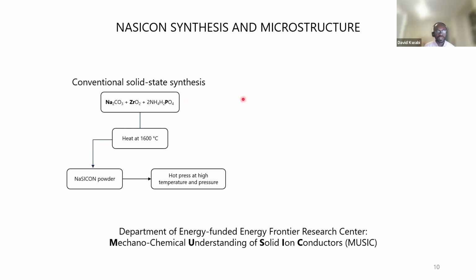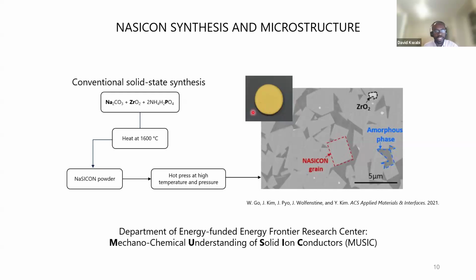One of the things we discovered fairly early on in our work is that the conventional way of synthesizing these NaSICON membranes gives rise to a very heterogeneous microstructure. The traditional way one synthesizes NaSICON is you take powders of sodium carbonate, zirconium oxide, and phosphate, mix them together, and heat them at about 1600 degrees C. That results in a NaSICON powder, which you can then hot press at high temperature to end up with a pellet of your NaSICON material, which you can then put into a flow battery. It turns out these materials are indeed excellent at preventing crossover.